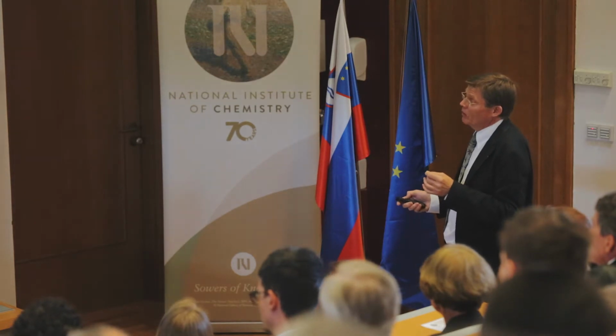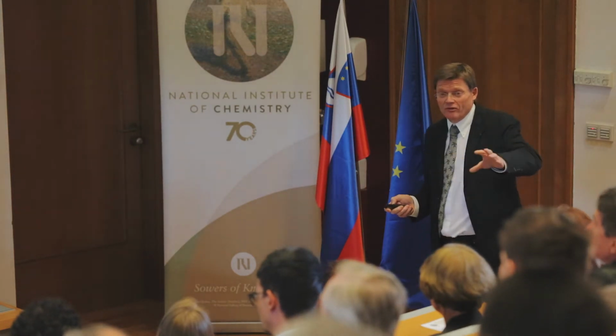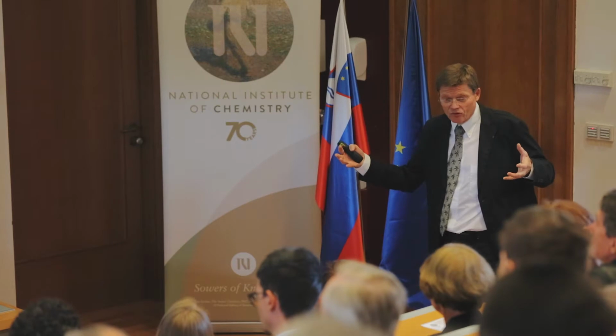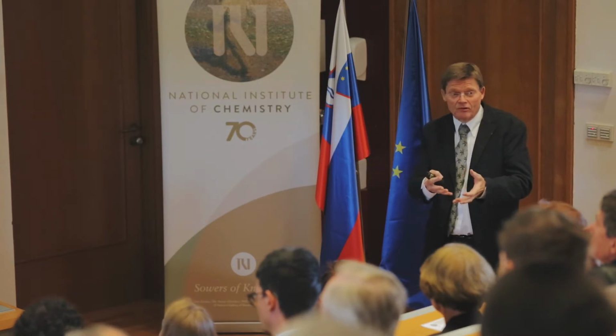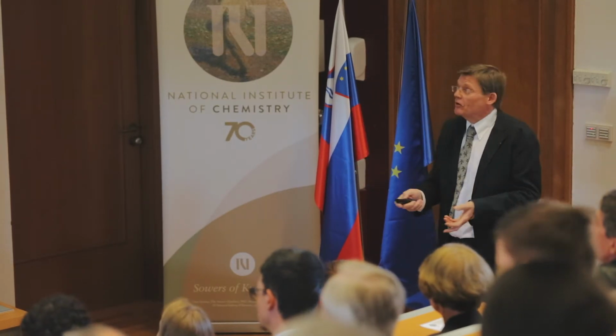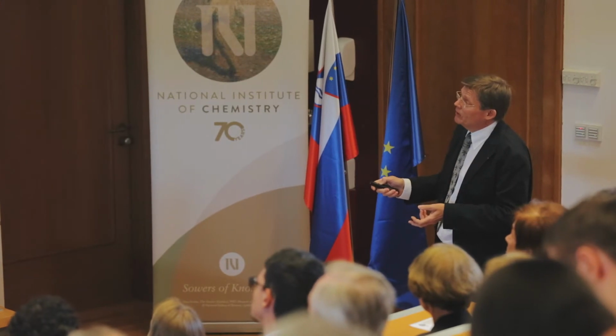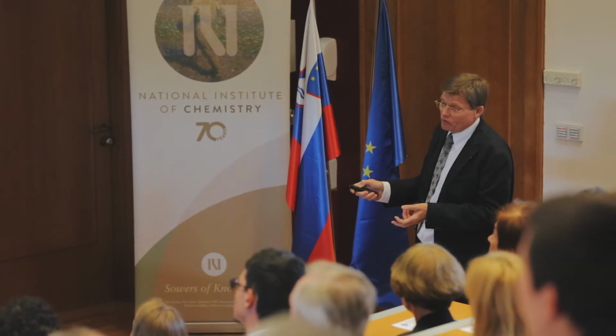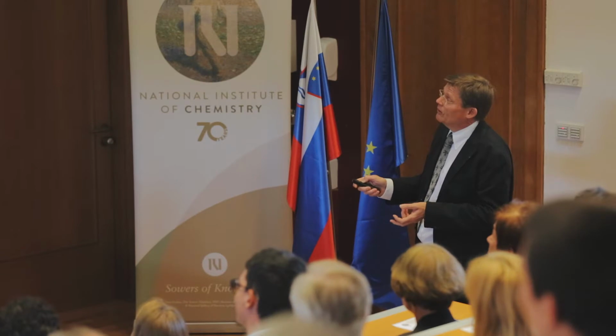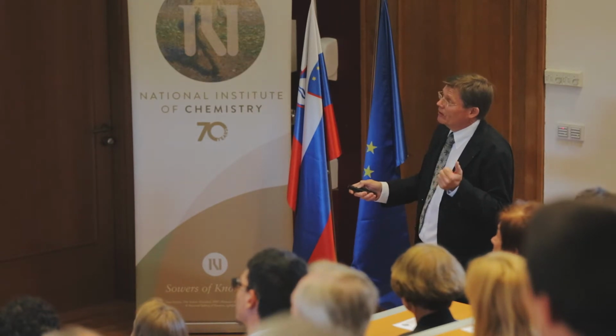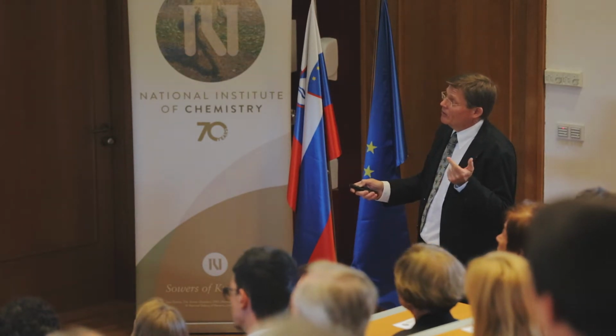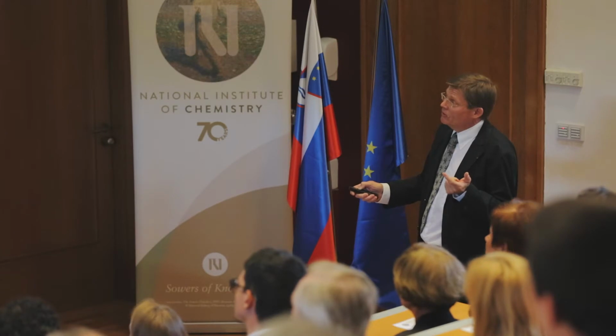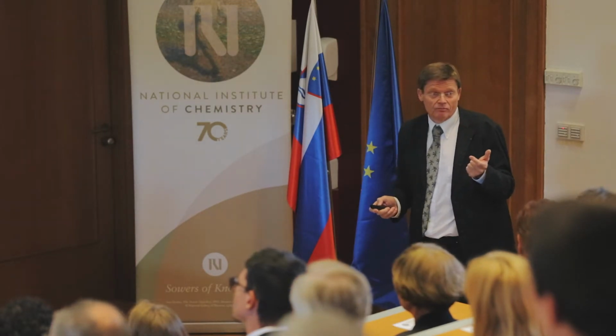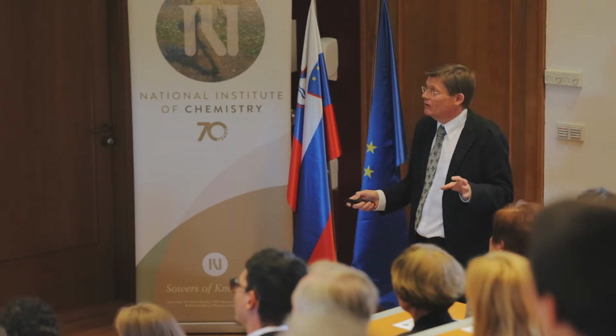What if the grain boundaries are very, very fast? They conduct, or they bring the oxygen directly to the small crystals, very, very fast. Then your time constant will be determined by the diffusion in such a small grain. So it will be determined by the chemical resistance of the grain and by the chemical capacity of the grain, but the geometry is very different. And then you directly get the result.